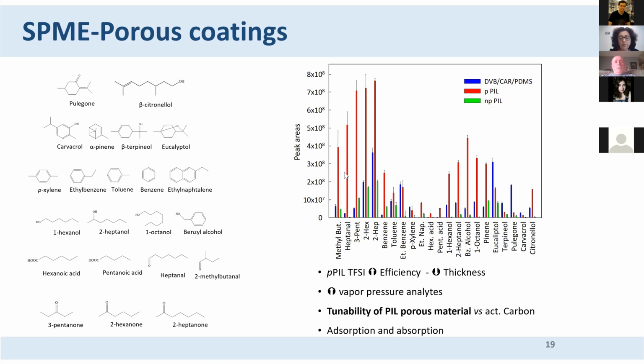Then realize the comparison of our porous fiber with the DVB/Carboxen/PDMS. Again, the peak areas are much higher for this fiber that we prepared with porosity, and it's not very thick, it's 20 microns thick. And it can really sorb the analytes that have a higher vapor pressure. So analytes that do not have a very high vapor pressure, the heavier ones, are more difficult to sorb.